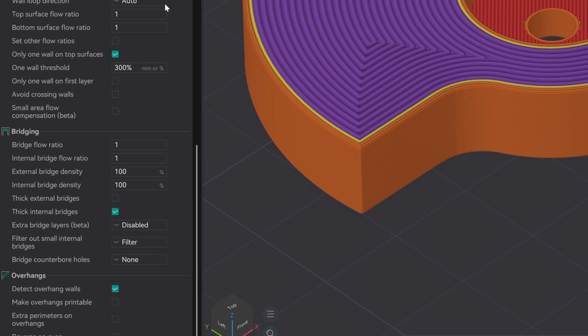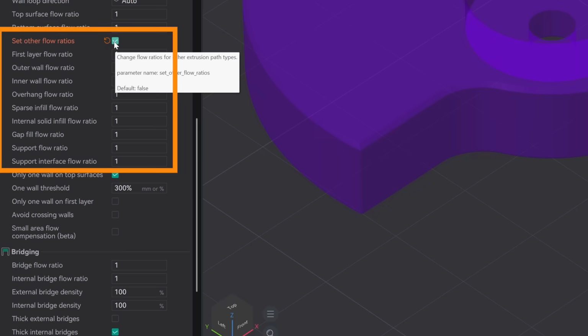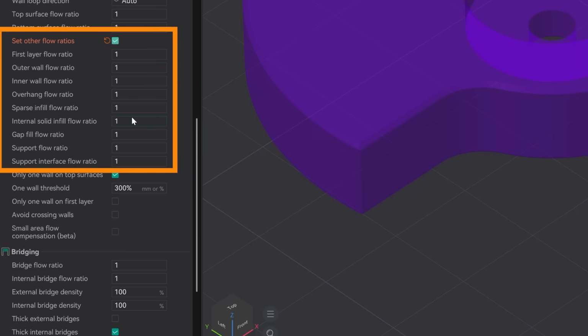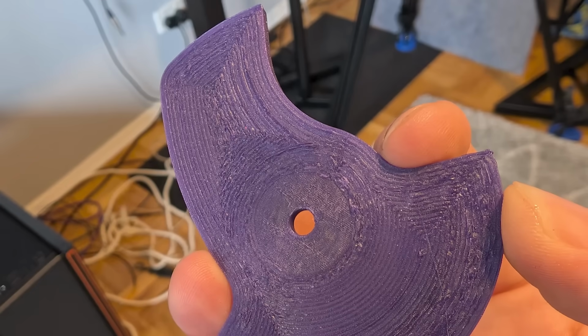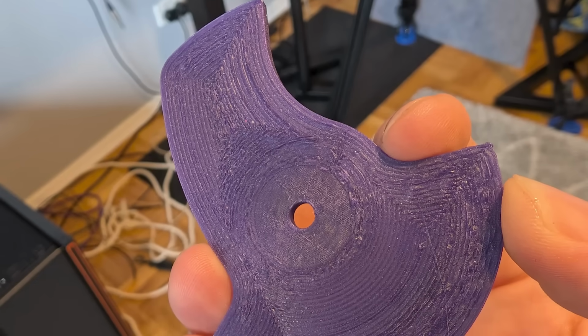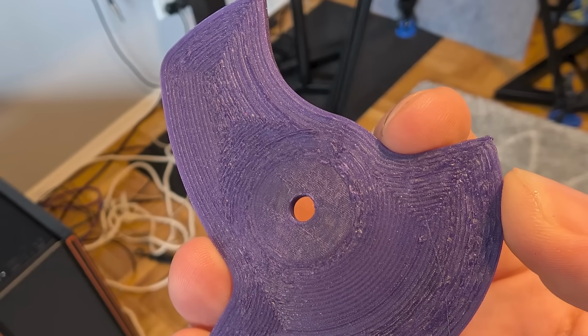closer each time. And as a bonus, fresh off the press for OrcaSlicer 3.2.3 is a fancy new way of squeezing even just a little bit more strength out of this part, a feature called specific flow ratios. It's a really old trick, but you can actually force your printer to over extrude slightly by forcing more plastic out of the nozzle than you would normally, which would then force more plastic into the part, smushing the layers together a little bit better to add more strength.